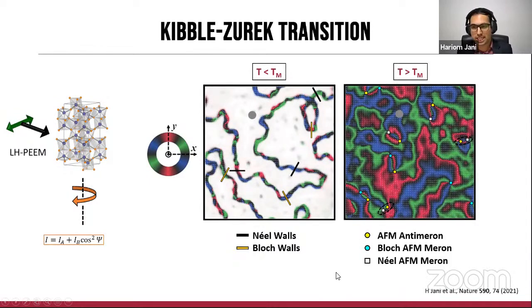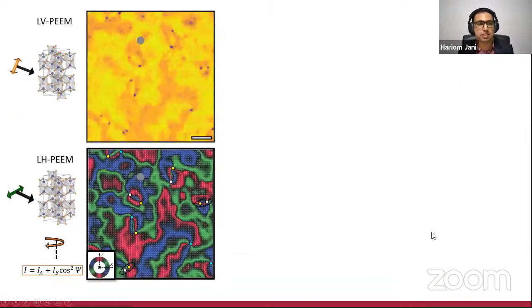At the room temperature state, we now observe a rich mosaic of in-plane domains, many of them consisting of trivial domain walls and some pinch points which actually have a topological structure. Now, in order to convince you that they are topological, it's best to compare the image at the same position between the linear vertical and the angle-dependent linear horizontal images. And here there is clearly a one-to-one correspondence: wherever there are these pinch points, there are corresponding out-of-plane bubble regions.